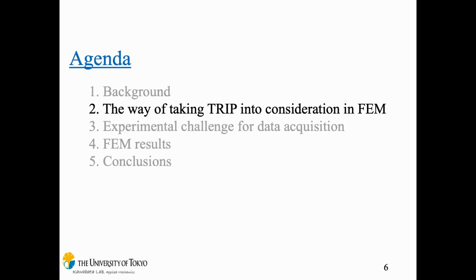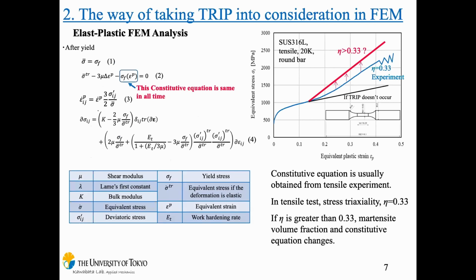So, how to develop a new FEM considering TRIP. Okay, so in the elastoplastic FEM, the constitutive equation is necessary. The constitutive equation means the relationship between the equivalent plastic strain and the yield stress. And the constitutive equation is usually obtained from a uniaxial tensile test, but for austenitic stainless steel, this way is not appropriate